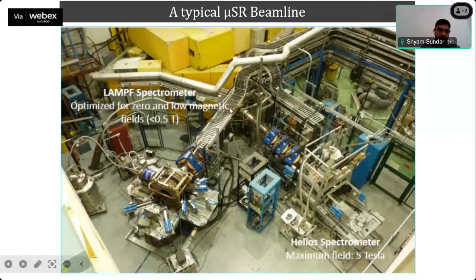This is how a typical mu-SR beamline looks. As you can see, this is the experimental station. This is where the muon beam comes from. These are the magnets to focus the muon beam. And here is where we do the experiment. This is the Helmholtz coil to apply the magnetic field. And these are the positron detectors, where we detect the positron after the muon decays in the material. We can do these measurements down to the millikelvin range, 20 millikelvin we can achieve. Here we have to connect it to a cryogenic system to achieve the low temperature. This is a photograph of the muon beamline at the Canadian TRIUMF particle accelerator.